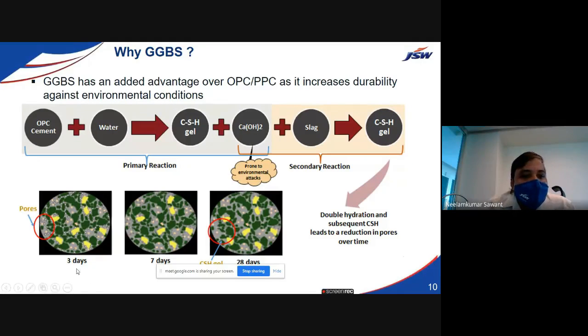You can see on the bottom, suppose I'm casting a concrete or making the concrete. So definitely after 3 days, you can see this is one of the microscopic pictures. So many pores are there. And after 7 days, as the concrete gains strength or it dries, definitely it contracts. And whatever the pores are there, those will be evolved and it will be dense and the pores will be decreased. But after 28 days, whatever the remaining pores are there, that space will be occupied by this secondary CSH gel and the GGBS particles. And definitely because of the double hydration, it leads to less porosity or reduction in the porosity in the concrete.